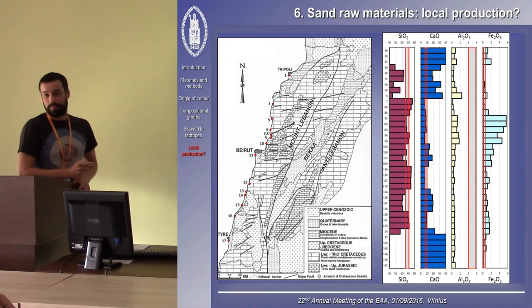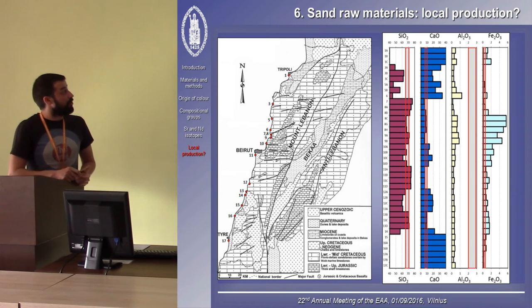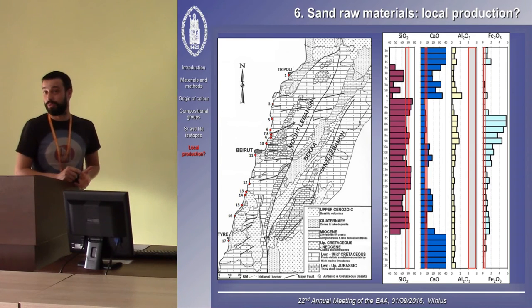Our major problem is actually in the aluminum. When we compare our concentrations in the calculated glasses from the sand to the range we actually find, we can see that our sands are very low in aluminum compared to the glasses. So, although I have no doubt that these sands can actually be melted into a glass, they would produce quite a decent glass, these compositions could not correspond to the glasses we actually find in Beirut. We have to conclude that the glasses in Beirut were probably not made locally.